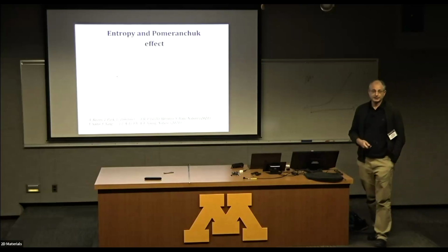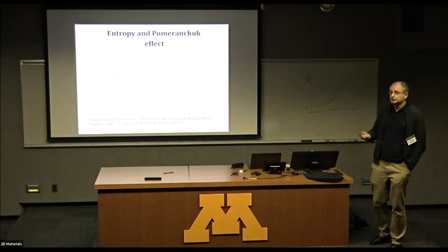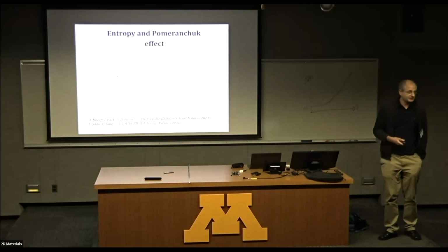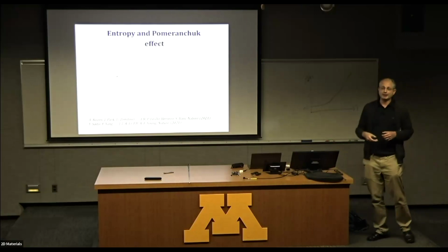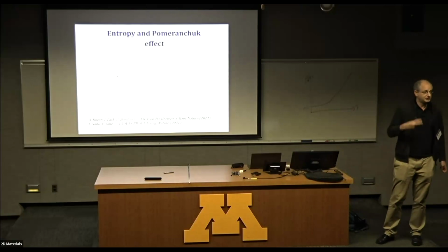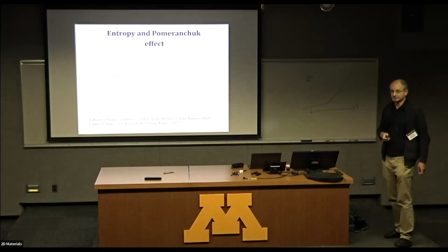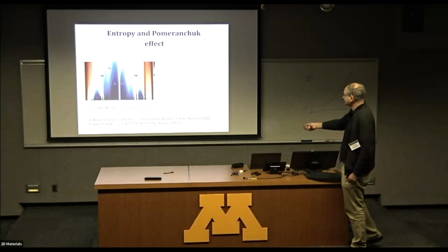On the other hand, we know that these systems can display behavior that we would associate with localized moments. If you have localized moments over a broad range of temperature, you should expect a large entropy, which is quenched by a Zeeman field, and this is exactly what's observed. The first hint of that came from transport.